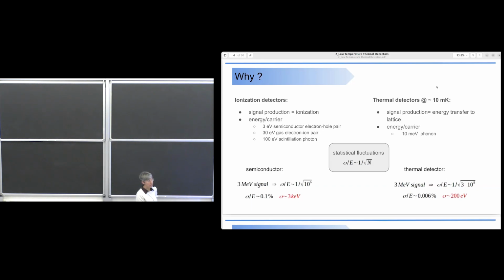Sorry? N is the number of carriers that you are producing. So it is the amount of energy that you have deposited inside your detector divided by the energy that is needed to produce a carrier. So in this case, this example uses a semiconductor, therefore it is 3 MeV divided by 3 eV. So the number of carriers is 10 to the 6. While in this other case, I used the 10 millielectron volt.